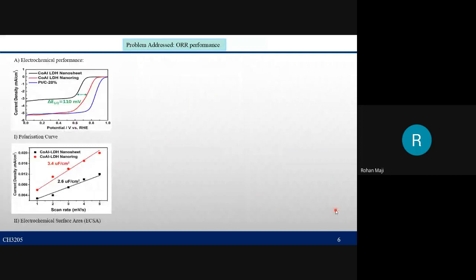Now, they use ORR activity as a probe reaction to study the structure-catalytic activity relationship of the nanoring. As we can see here, the nanoring exhibits a higher ORR onset potential at around 0.88 volt and a higher half-wave potential, approximately 0.74 volt, over 110 millivolt compared with the nanosheet. This indicates the higher intrinsic activity of the nanoring.